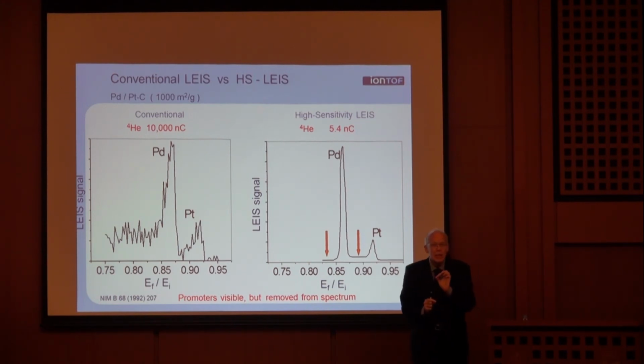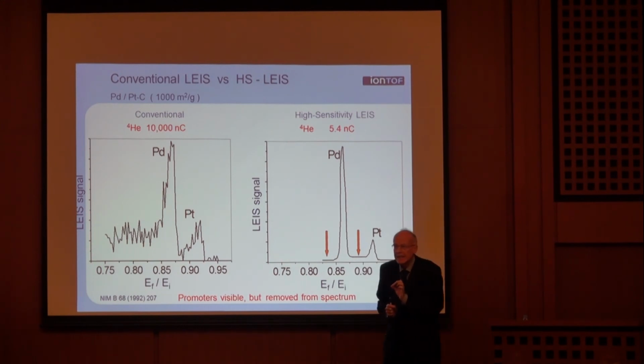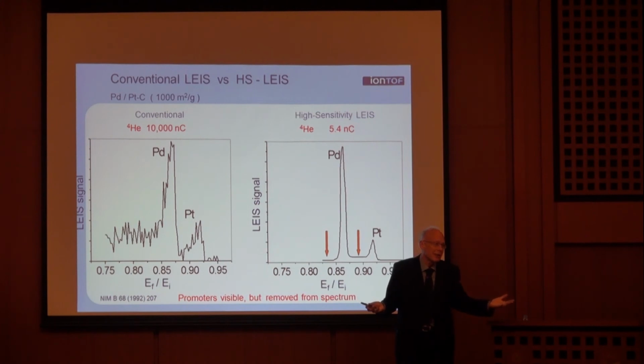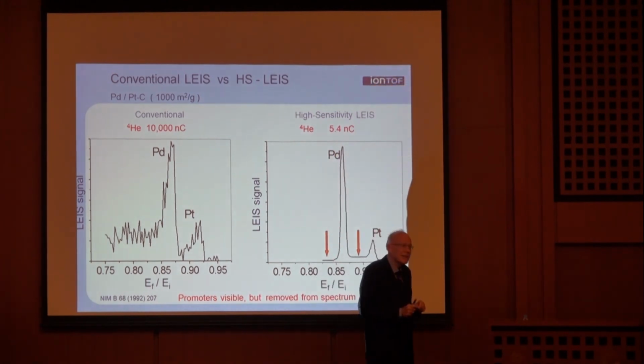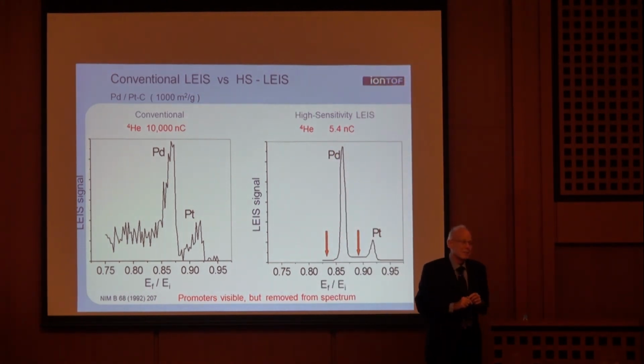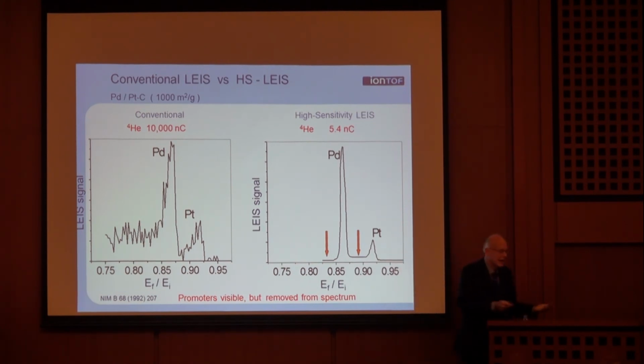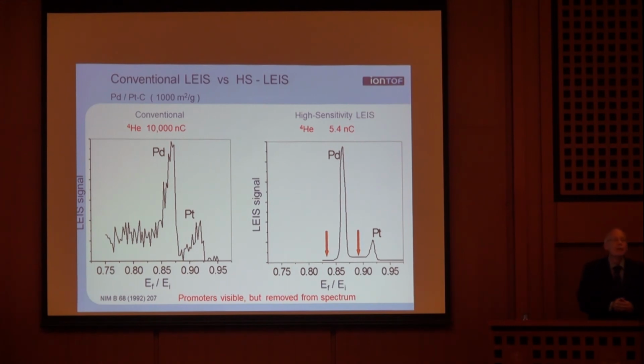Why? Because the sensitivity of the technique is such that we can see promoters. So it's not only palladium, platinum, but there are tiny additives. But they are secret, so I cannot show you. Just because here there are people who know a lot about catalysis, I don't want to give them great ideas, so I just made that background myself here. But you see the statistics is much better, and that is why now, even for very rough catalyst, we, in a standard way, can do analysis.